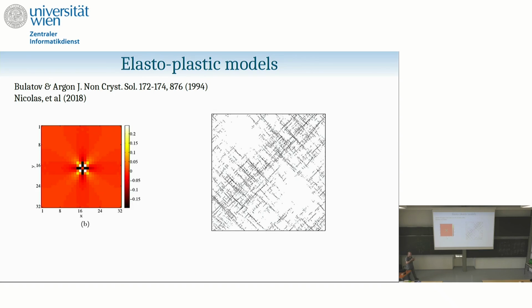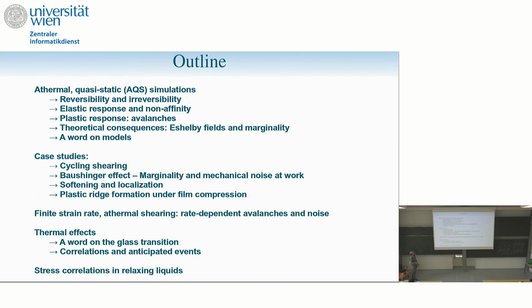You have elastoplastic models where people now try to look at the elastoplastic response. You have systems where you imagine spin-like systems with many sites, and you can trigger events, construct a variety of rules for how you trigger the events, and then introduce these Eshelby fields, and you do produce avalanches. And then maybe that might be a good time to stop.